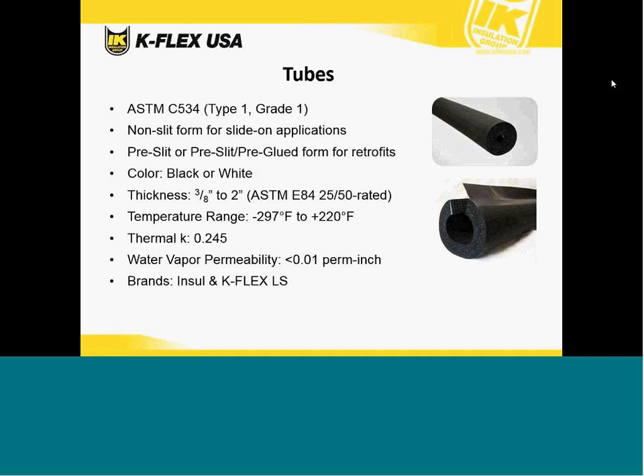Available in black or white, and in thicknesses from 3/8 of an inch up to 2 inches, and it's ASTM E84 25/50 all the way up to 2 inches. The temperature range for this product is from -297 Fahrenheit up to 220. The thermal conductivity is 0.245, and the vapor permeability is less than 0.01 perm-inch, which, as you know, is well below the ASHRAE Class 1 vapor retarder line.